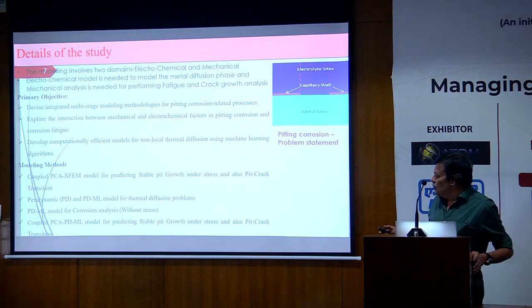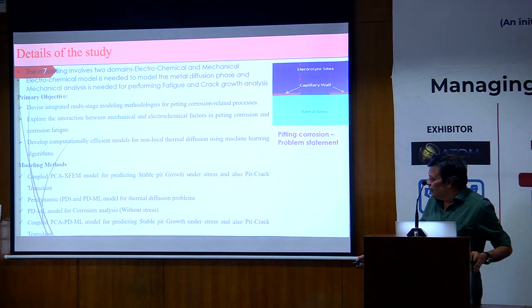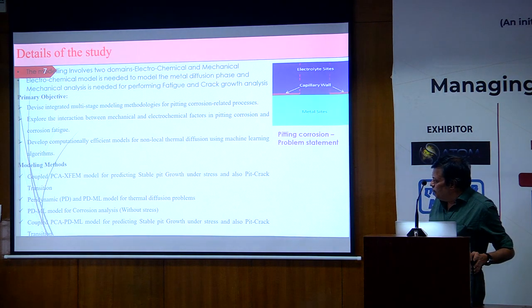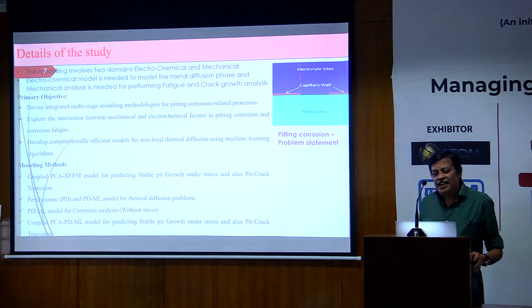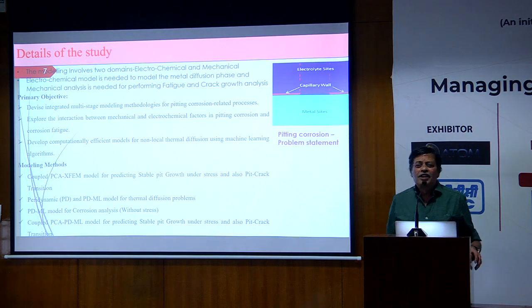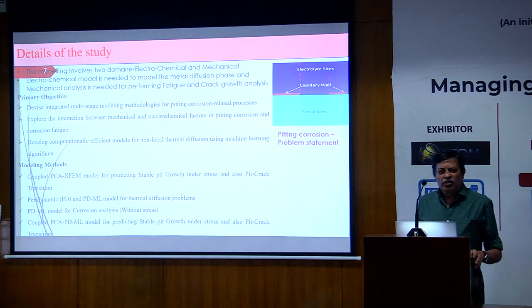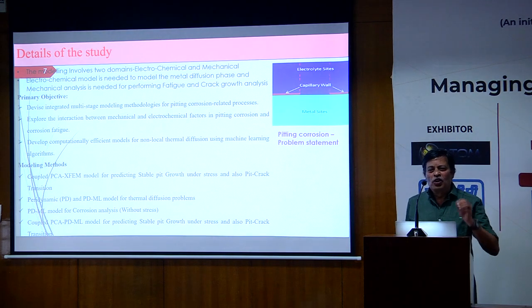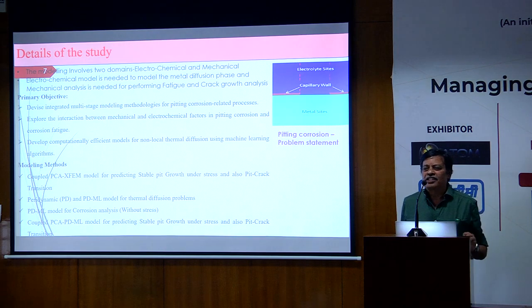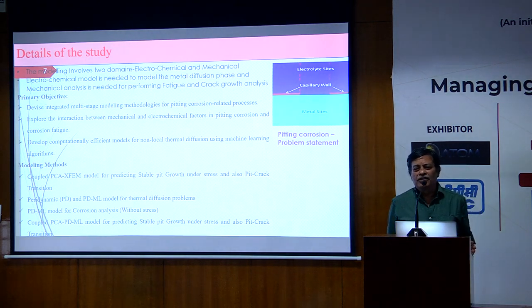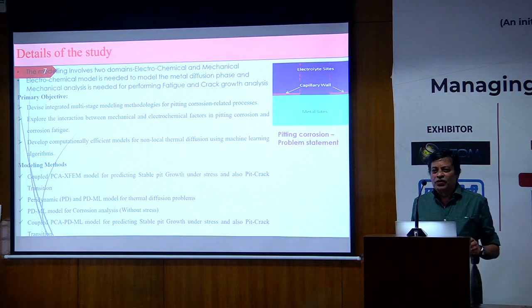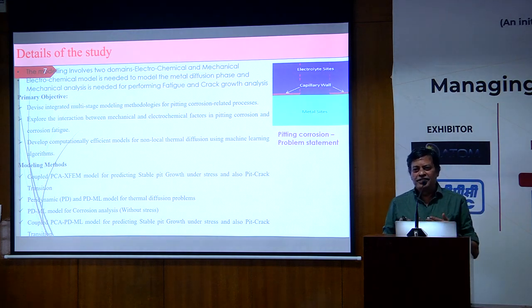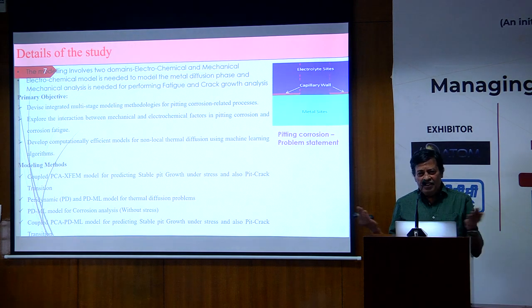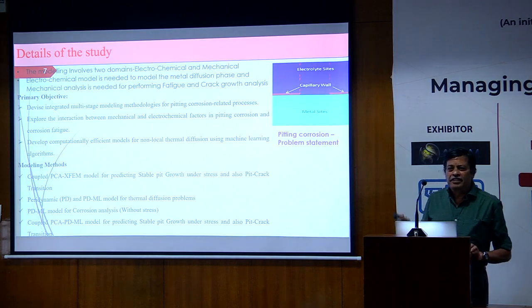And we used basically the PDML model, which is different from the PCA model. And we coupled PCA, PDML, everything. The ML stands for machine learning. Why? Because the peridynamic model takes an enormous amount of time. One run takes about 2 to 3 days. So we need to reduce the number of times that we do it. So we couple the machine learning approach with the conventional FE approach. We couple them together to predict the pitting process.